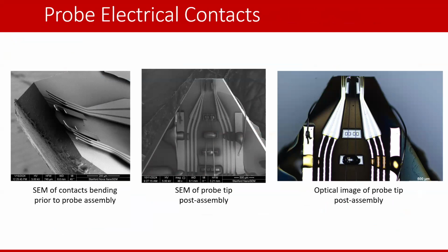The electrical tines, of course, need to touch before the optics touch, because if you remember from the way these resonators look, there's a bump that's the whispering gallery mode resonator, and then these electrical lines that are underneath. And so that means that with some very careful strain tuning on the electrodes themselves, we're able to cause them to actually bend. This is a little bit difficult to see, but if you look closely at this SEM, you can see that the electrical tines actually bend up to about 20 degrees past. And so this means that when you flip this whole assembly upside down and then attempt to couple to an optoelectronic device, the electrical tines will touch before the waveguide will, and you'll get electrical contact and then optical contact. And this additional pressure keeps it down, even with the cryostat vibrating. And so this is some SEMs and then an optical image of the same thing.